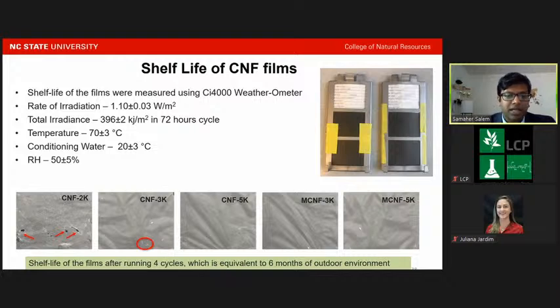harsh environment. It was okay until the third cycle, but when we used the fourth cycle, it kind of ruptured. And there was slight rupture in the nanofibrils produced at 3K also. However, when you move to higher energy, that's 5K, and for the modified nanofibrils, it could withstand up to the fourth cycle, which is equivalent to 6 months of outdoor environment, which shows that the higher energy as well as the modification improved the mechanical and the tensile strength of the nanofibrils so that it could last longer for outdoor activity.